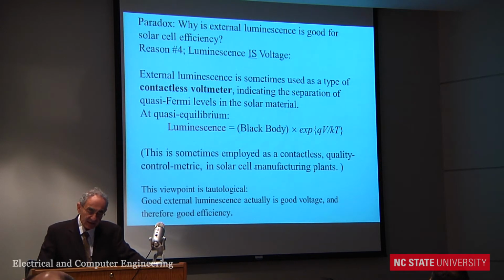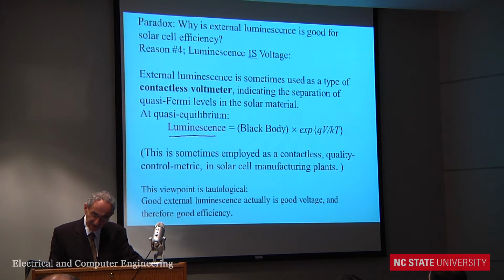To me, it's tautological. When you measure the luminescence from a solar cell, you're effectively measuring the internal voltage. Now, I can show you that there's a formula you can derive from statistical mechanics. The luminescence is proportional to the NP product. You can generalize this. The luminescence is proportional to this factor. So the more luminescence I have, the more voltage I have.